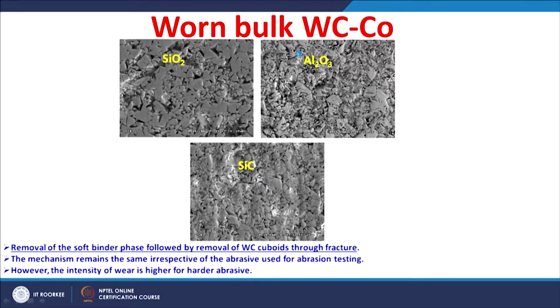The worn surface analysis is also studied for the bulk as well as the coating. The bulk tungsten carbide cobalt material after wear shows there is a removal of this binder phase. You can see the removal of this binder phase, and then there is a removal of these tungsten carbide cuboids by cracking. You can see a lot of cracking and then their fracture. So, the mechanism is like that. First of all, the binder phase is removed, followed by the cracking of these tungsten carbide cuboids which stand on this surface. Once they fracture, the total material has failed.